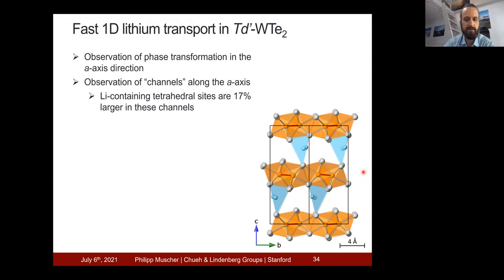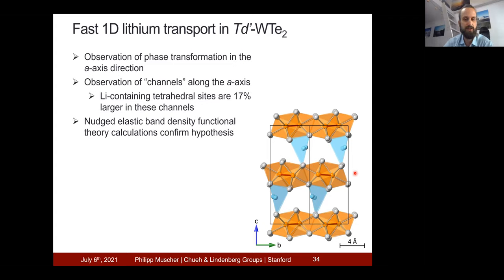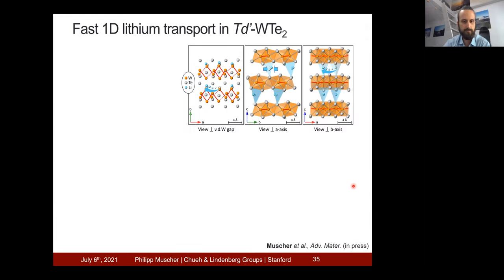So this suggests that the transport along the A-axis might be really fast. So we used nudged elastic band density functional theory calculations to confirm that hypothesis. In this technique, we look at the energy diagram along the path of an ionic hop.